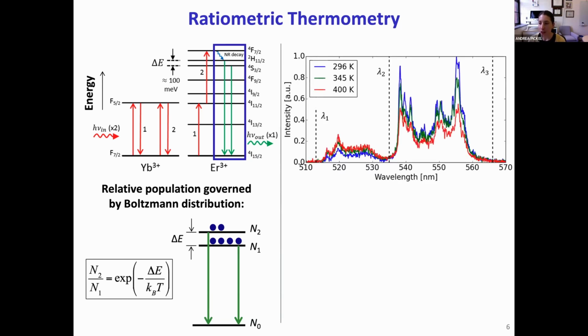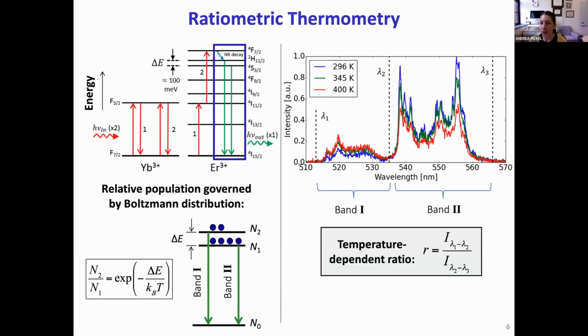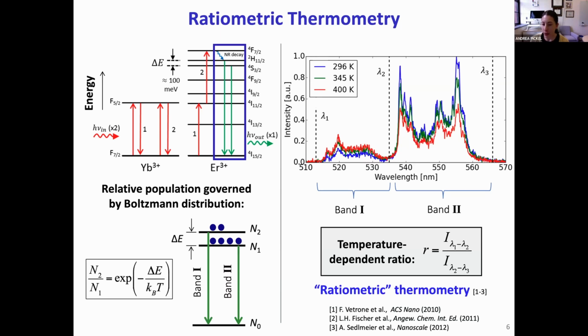And we can see that by looking at spectra taken at different temperatures. So if we divide the emission wavelength range into two bands, lambda1 to lambda2 and lambda2 to lambda3, we see that when we increase the temperature, the emission intensity in the first wavelength band, which corresponds to the transition from the higher energy excited state to the ground state, increases relative to the intensity in the second band, which corresponds to the transition from the lower energy excited state to the ground state. We can then define a temperature-dependent ratio as the integrated emission intensity in the first wavelength band divided by the integrated intensity in the second band. And this approach is known as ratiometric thermometry.